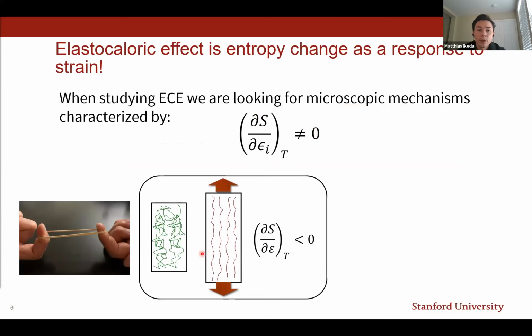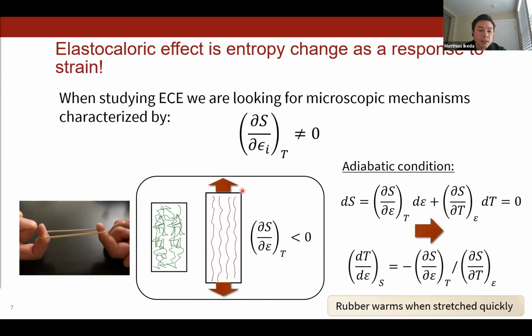And in natural rubber, there are polymer chains that will align under tensile strain. And so it's very clear that this reduces the entropy, as shown here in the middle panel. And so we have here a dS/dε at constant temperature that's smaller than zero. Now, if we were to apply tensile strain really quickly, such that no heat can flow into the rubber band or out of the rubber band, then we are in so-called adiabatic conditions. And under adiabatic conditions, the entropy cannot change. So what we have to have is a balancing contribution. And this balancing contribution originates from a temperature change. And this temperature change as a response to strain is very closely related to the elastocaloric coefficient at constant temperature. And it is this temperature change as a response to strain that we will measure in our experiments.